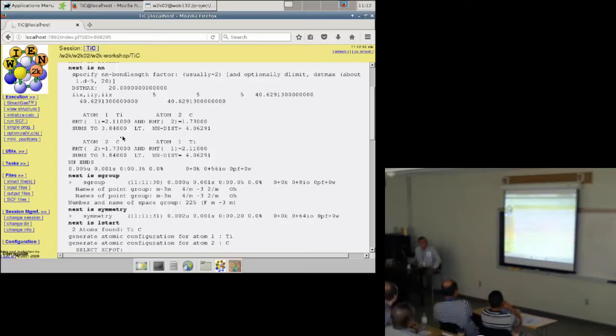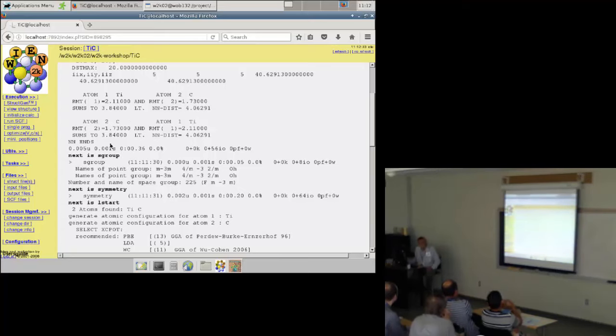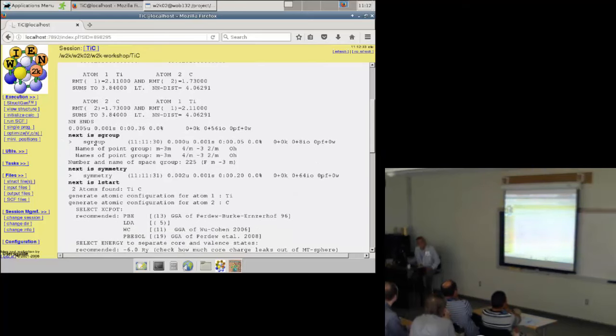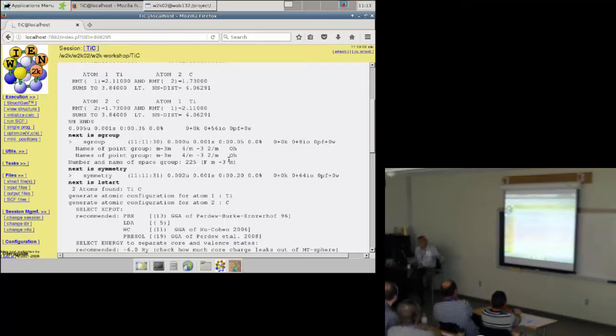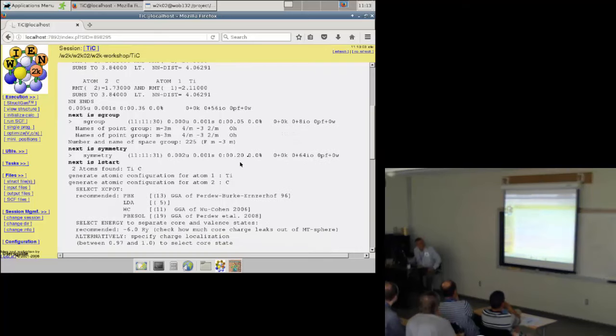Here you check whether your atoms are correct. In unknown or handmade structures you may get an error here and should not continue if there are warnings. The next program is called 'sgroup', which calculates the space group for you — now we know it is space group 225, Fm-3m. If you had put in the space group, hopefully the same would come out. sgroup can also automatically reduce your unit cell to the smallest possible unit cell.